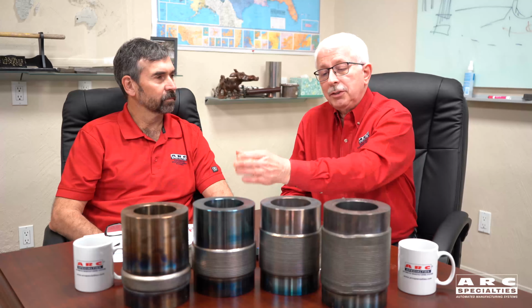So you didn't quadruple the amperage. No, it's not a proportional number. We probably went up, let's say 20 amps each time we stepped up our travel speed and deposition rate. So if we look at our heat input, amps times volts times 60 divided by inches per minute, when you start doubling, tripling, and quadrupling the denominator, our heat input drops dramatically. For an example, at 2 pounds an hour, we're probably at 19 or 20 kilojoules per inch heat input. When we get up to 8 pounds an hour, 9 to 10 kilojoules per inch. Faster deposition, lower heat input.